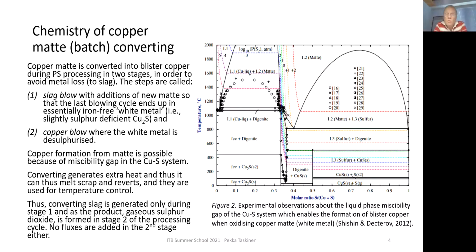And once all sulfur has been oxidized, we are here at a certain temperature, which we are using in converting. It's not 1400, it's between 1200 and 1300 in industrial operations. But anyway, the process goes exactly like that, and you can see from the phase diagram how the matte is behaving after the iron has been oxidized away. And then when we continue the oxidation, sulfur content is decreasing in molten copper. And what we have, as you will see, is crude copper containing sulfur and oxygen. I will tell you later why we have oxygen in there.